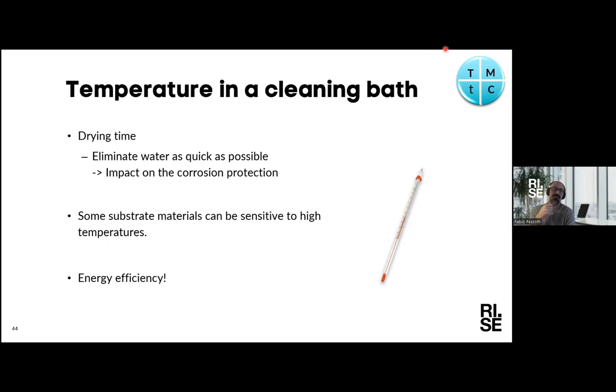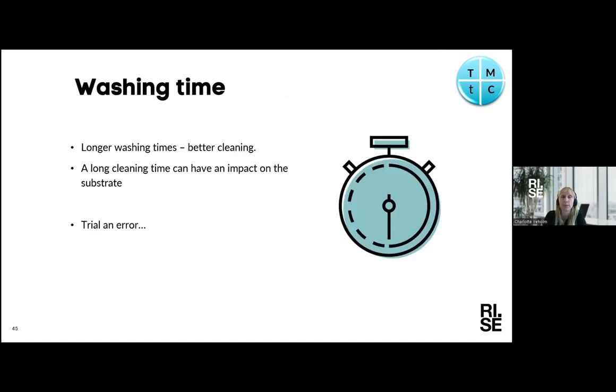And temperature can also be related to the efficiency of the cleaning chemicals, or they can be more efficient at higher temperatures than at lower temperatures. Yeah, exactly. Yeah, true. And it's the same with the washing time. If you have a process, you can't have too high time or too long time to be efficient. So that is, of course, steering how the washing time can be. And this also, of course, can have a large impact on the substrate, and also on the chemical used, so to say.